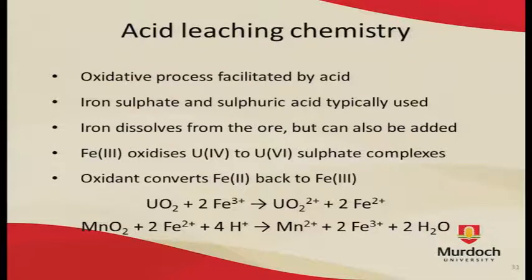While the process of acid leaching is described as acid leaching, it's more like acid-facilitated oxidative leaching. The acid works to keep the uranium and iron in solution. Iron is being used as the oxidative medium. Iron sulfate and sulfuric acid are the standard reagents for acid leaching. The iron will dissolve from the ore itself, but it can also be added to increase the oxidizing strength of the solution.